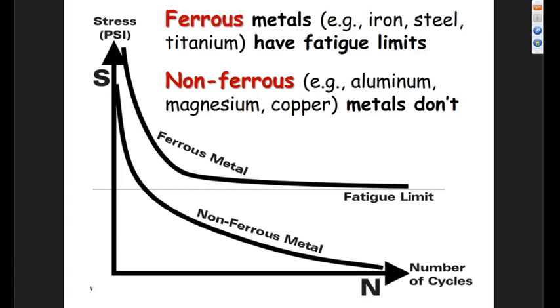below its fatigue limit, and so it really doesn't feel the repetitive stress unless it for some reason is operated above its fatigue limit. For example, a prop strike or a violent pre-ignition event or something that stresses the crankshaft beyond the level of stress that it's really designed to handle. Then, of course, it could develop fatigue problems, and that's why after a prop strike, we always have to do a whole bunch of non-destructive testing on the crankshaft to see whether it has developed any cracking. But under normal conditions, something like a crankshaft will never crack because it's made of ferrous metal, made of steel, and it is designed to operate below its fatigue limit.